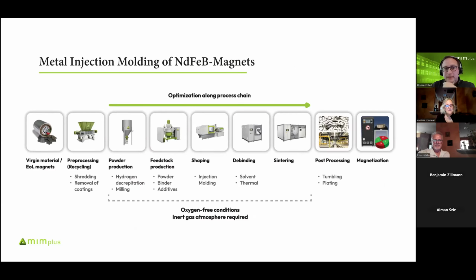What we did in the last years of the development of our process was optimization of nearly every process step in order to achieve a magnet grade that is comparable to a press-sintered magnet. What is also important to know is that from the powder production up until we have the sintered part, we need oxygen-free conditions. As neodymium has a really high affinity to oxygen, and every ppm of oxygen in our final magnet will reduce the magnetic performance.